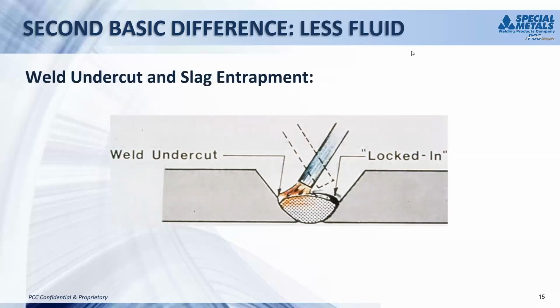Go ahead, John. This is a drawing of a cross-section of a weld. If you can imagine you're the welder and you're welding from one side to the other, and the other, and the other, you should not use a whip weave. That's common among steel welders. If you can imagine what it's like when the electrode goes to one side and burns into the sidewall, it leaves a little undercut there. And if you move the electrode away too quickly from that, the weld metal doesn't have a chance to catch up and fill in. But what happens is the slag is designed with a low viscosity, and so the slag will fill up that undercut.